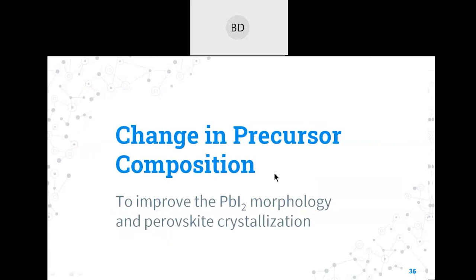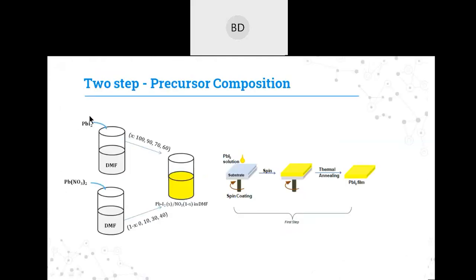Now the next approach that we have used is the change in the precursor compositions. So what we tried is we changed the PbI2 morphology by changing the precursor composition of the PbI2 itself. Earlier, we were using only PbI2. In this case, we have introduced some amount of lead nitrate as well. So we have used some volumetric ratios for PbI2 and lead nitrate and made a precursor solution. The volumetric ratio is varying from 90% of PbI2 and 10% of lead nitrate to 60% of PbI2 and 40% of lead nitrate. We have made the PbI2 film using these precursor solutions.